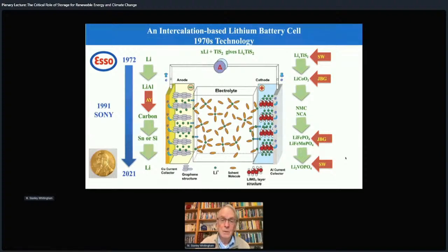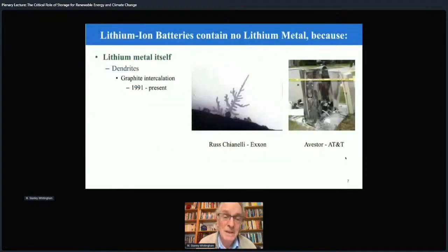So why don't we use lithium metal in lithium batteries? This is why, and this is a study that Russ Chianelli did at Exxon about 1975. When you charge a battery, you're electroplating lithium out. So you've got one electrode on this side, this one. As soon as you get these little protuberances formed, then the electrical field between this tip and the other side is higher. So they then grow exponentially. So the difficulty in lithium batteries is to stop these dendrites falling straight through the normal separator. If they do that, then you have fires, as in this case AT&T had in Texas.